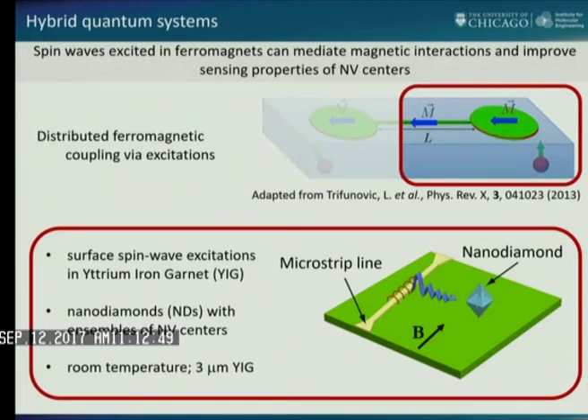Let me show you. So we started to use YIG. For those of you who might not be familiar with YIG, it's sort of the hydrogen atom of magnets. It's a garnet material. The spin waves in this material, if it's clean, can go many feet before they begin to damp. They're very, very clean magnetic materials.